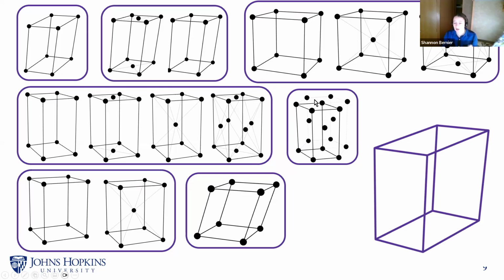I do want to note that the hexagonal lattice is one that frequently trips people up. The hexagonal lattice is actually 3 parallelepipeds that are repeated around a central axis. So even though if you were to look at a real crystal, the atoms would appear to be oriented in hexagonal symmetry, basically, so that they had rotational symmetry, it only takes the description of a single parallelepiped, one third of those atoms, to be able to replicate the whole crystal structure. So even though the hexagonal crystals are a different shape than all the other crystals in macro space, we can still talk about parallelepipeds.